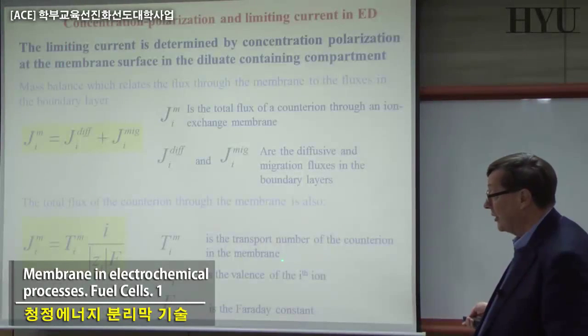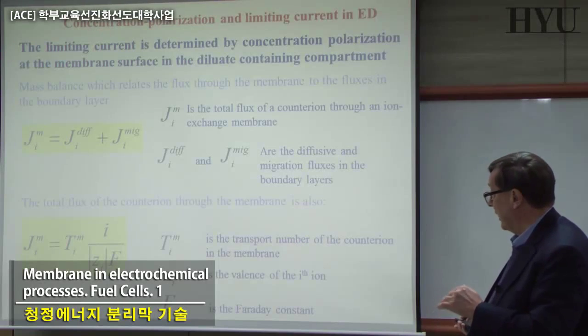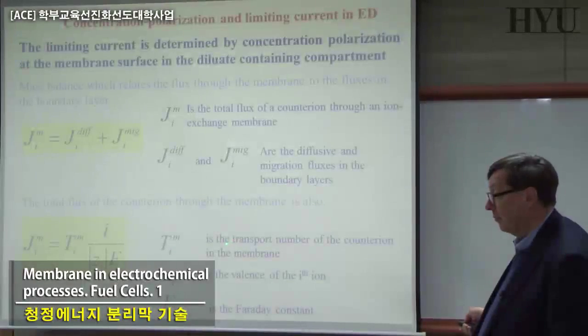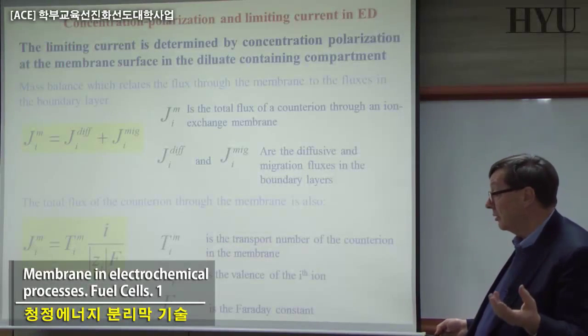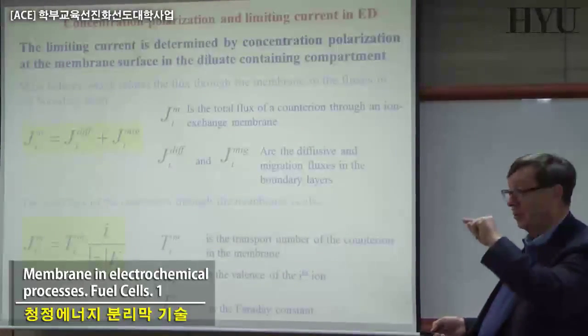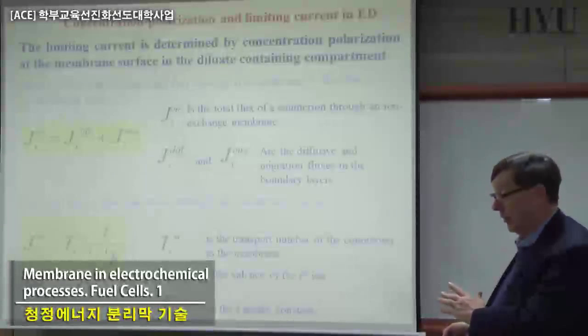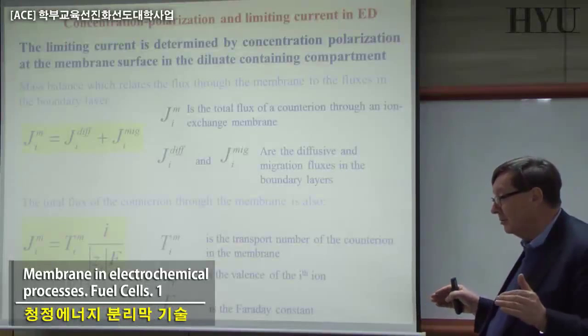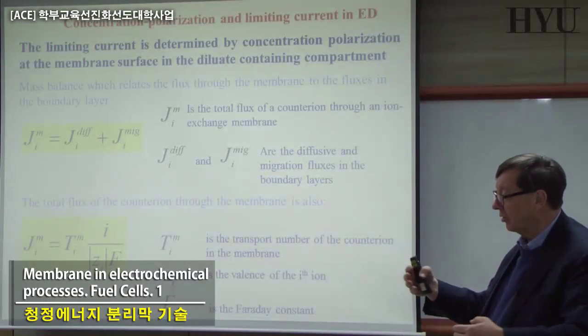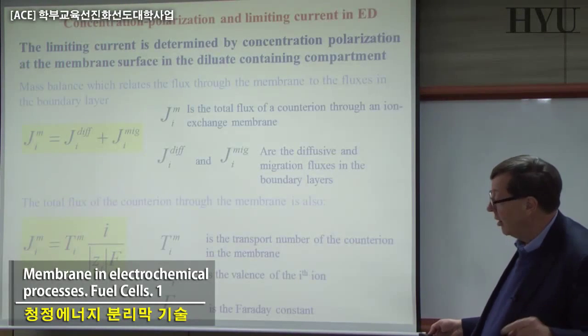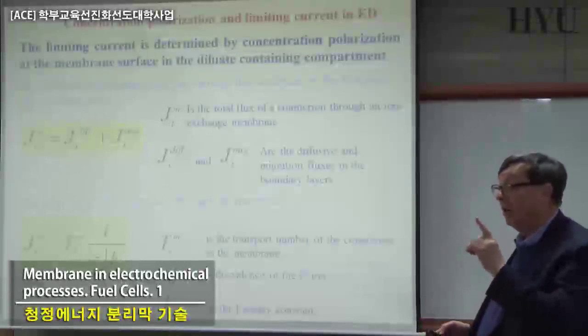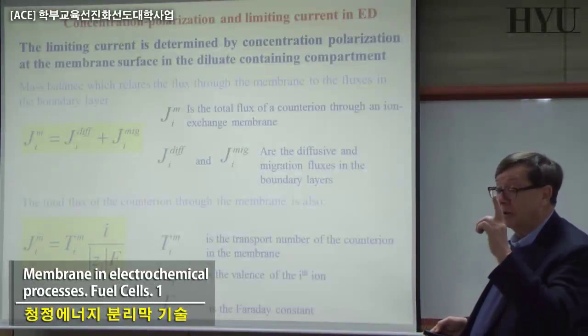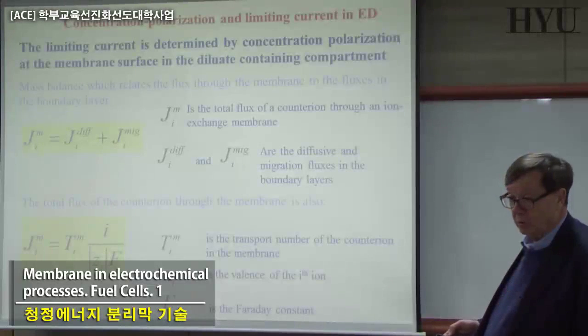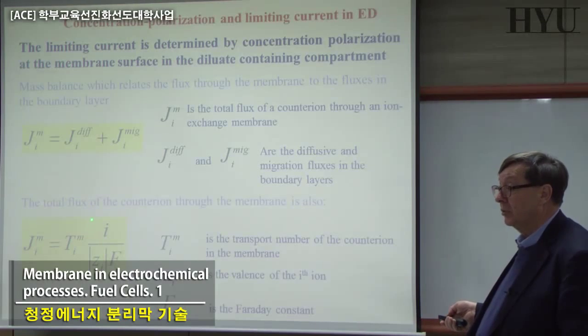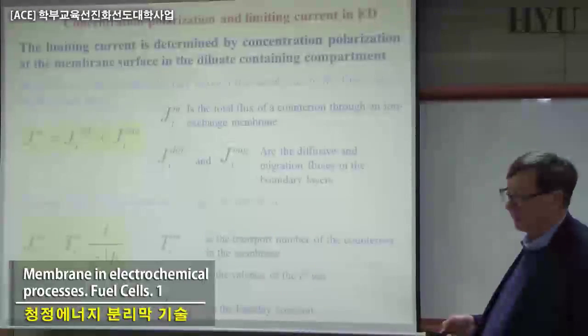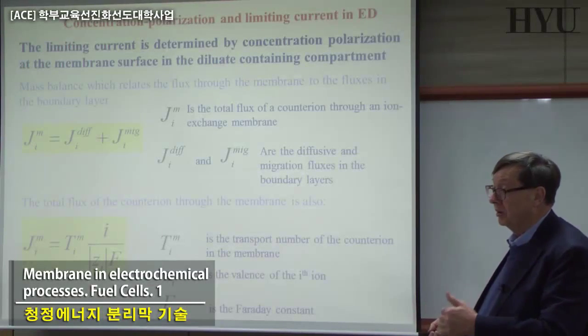So the co-ions are the ions having the same charge, and the counter ions are the ions having a different charge. We define a transport number as the ratio between the amount of current transported by one ion with respect to the total current that is transported across your membrane, which means that if you have a membrane with no selectivity, positive ions and negative ions both will go across the membrane. So the transport number will be 0.5. If you want to have a fuel cell in which only the proton H+ has to go through, that has to be 1, not 0.5. Otherwise, it means that some other ions are going through. So this one has to be 1. All the current will be transported only by the H+ ions. On the other side, there will be no current transported by ions with a different sign.